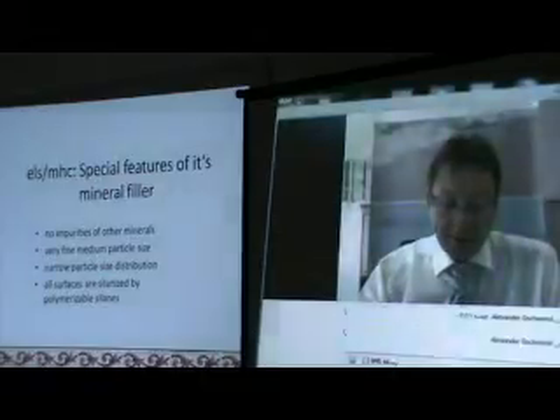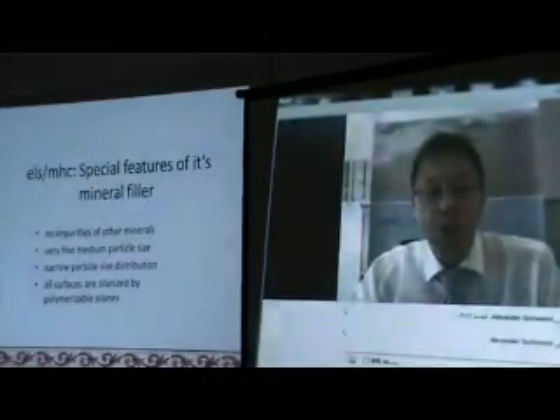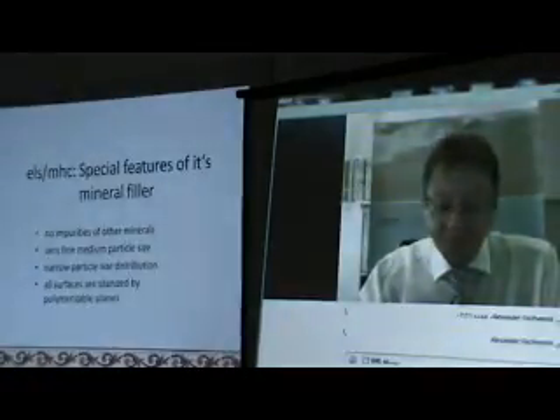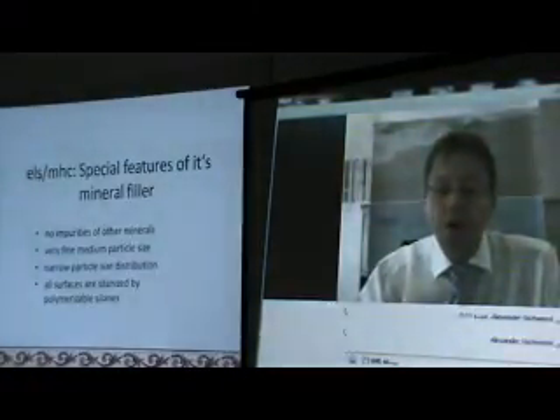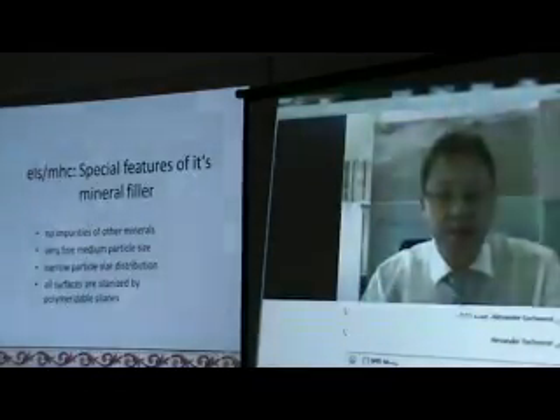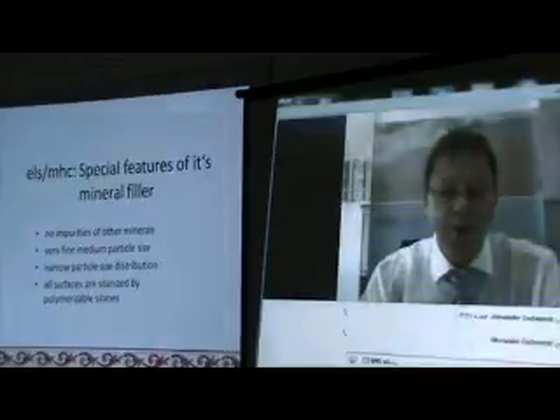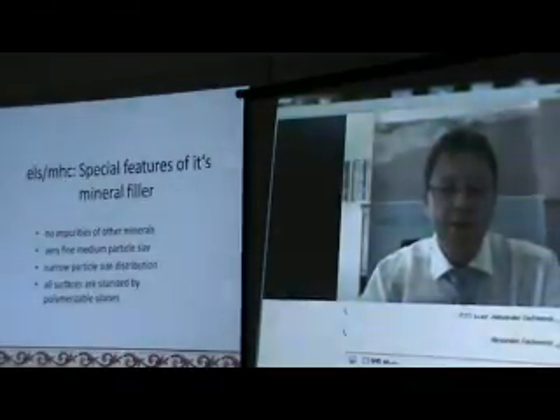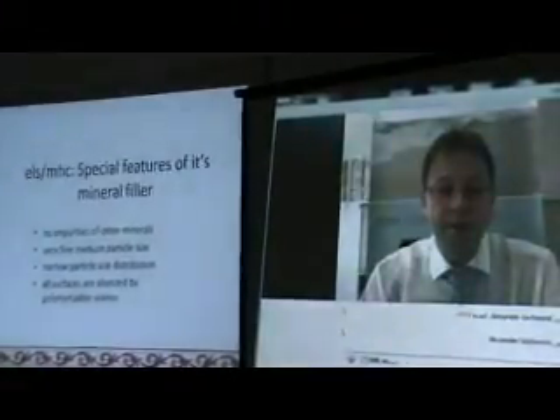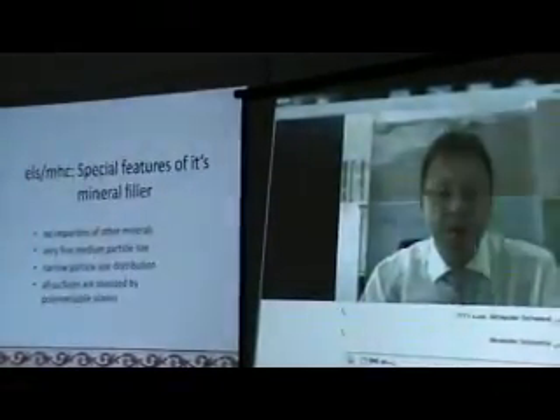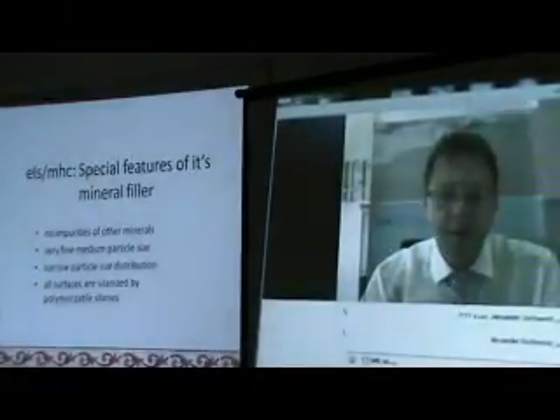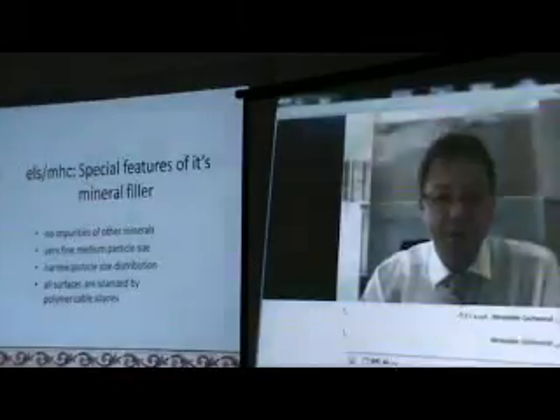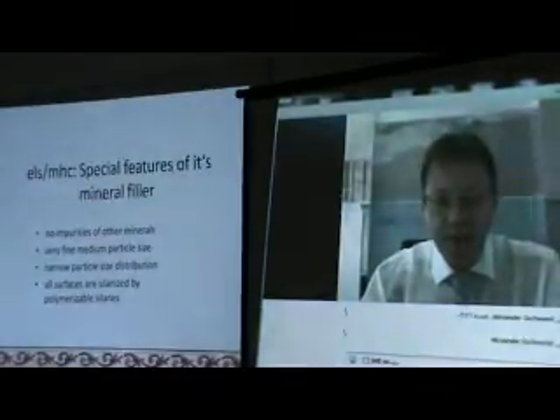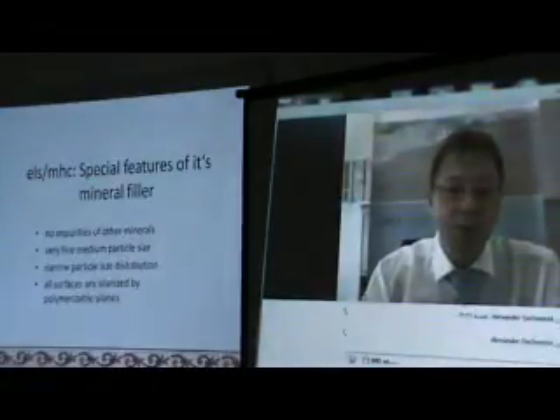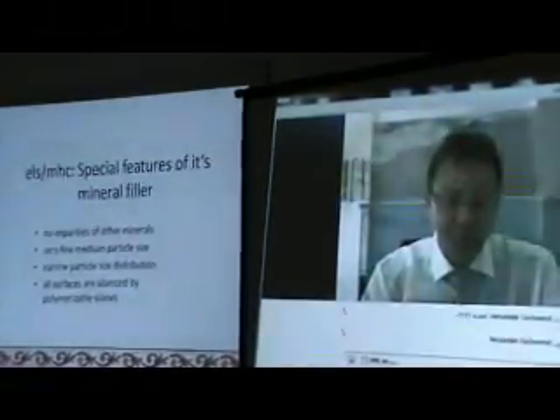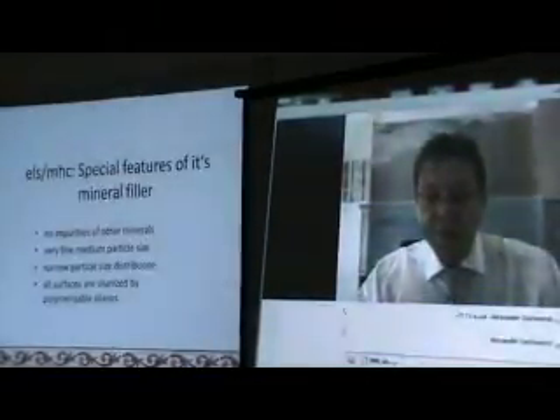So then it is important the quality of the silanization of the glass fillers, because you must understand that the glass fillers by themselves cannot chemically connect with the resin molecules. Therefore, the glass filler must be submitted to a treatment of the surface. This is called silanization. The silanization is a coating of the glass filler, and this will make the link between the glass particle and the resin molecules. Next slide, please.